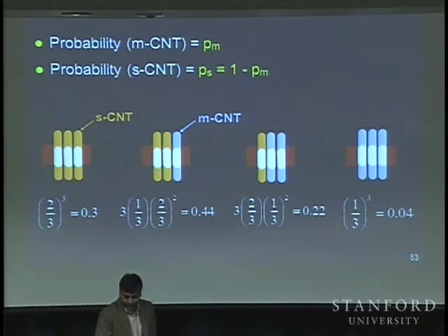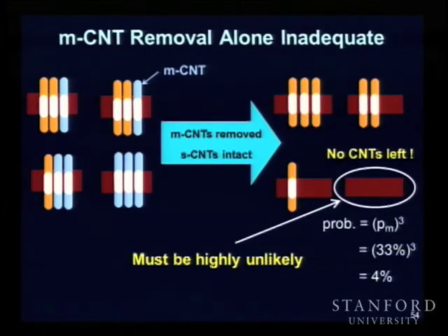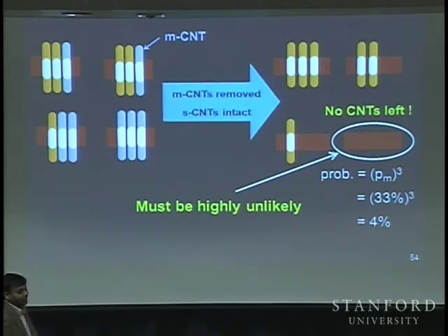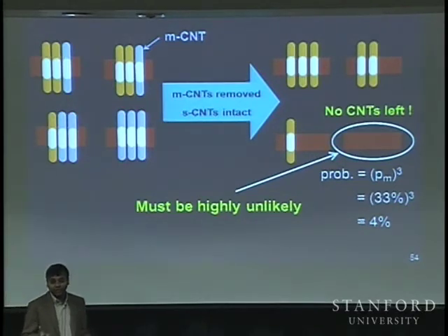And now, even if I had a perfect metallic carbon nanotube removal process, right? I said 99.99% of the metallic carbon nanotubes removed. Let's take an ideal situation where 100% of the metallic carbon nanotubes were removed and 0% of the semiconducting carbon nanotubes are removed. That's kind of a great situation to be. I end up with a situation where this particular transistor does not have any carbon nanotube left. So essentially, I got a yield problem, right? So this is to show that this essentially becomes a probabilistic system.